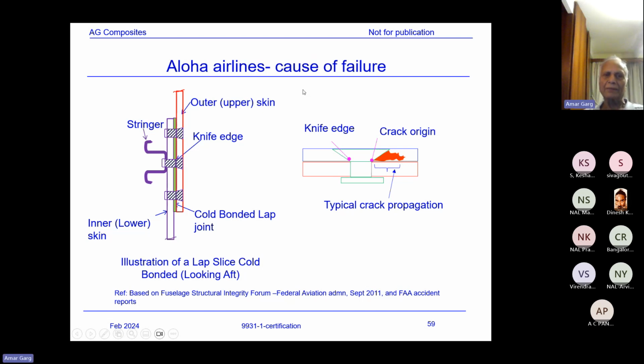Earlier, when this aircraft was designed, they used to have a cold bonded lap joint. The cold bonding might have failed. So during the bond failure, the bond was not taking the load properly, and all the load was taken by these rivets. And the rivets you are seeing are like a knife edge. So this knife edge created the cracks when the bond failed, because as long as the bond is intact, the bond will not allow the rivets to carry the load and the structure will be perfect unless the bond fails. But here it seems at that time the bond might have failed, which might not have been detected. It's very difficult to detect the bond failure, actually.